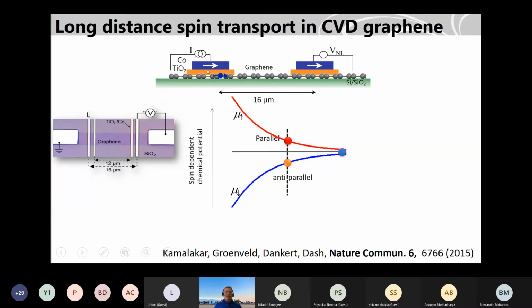Okay, so the device cross section looks like this. You have this cobalt ferromagnet, and a little bit of titanium oxide, around 1 to 2 nanometers. You want to inject spins from the cobalt into graphene, so they get accumulated and diffuse everywhere in the graphene. And what you do is put another detector here, in a non-local geometry.